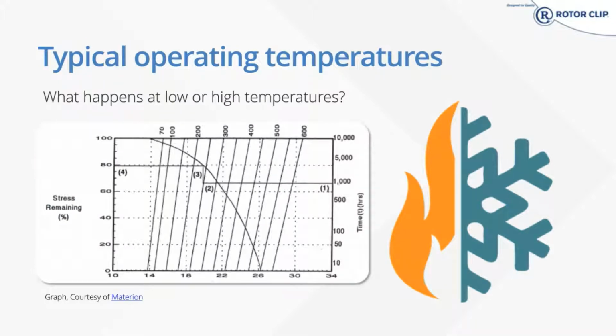So this is a graph that kind of shows what happens at higher temperatures. As the temperature increases, the performance of the ring decreases. So thrust loads are greatly reduced, material strength is reduced, and eventually the parts will fail completely. So if you're pushing the extreme limits of the thrust load of the ring, you usually want to be in the 100-degree Fahrenheit range. You could go 50 degrees below, 50 degrees above. As you start increasing towards the 400 degrees, 300 degrees area, you start to lose performance, and then at 600 degrees, complete failure usually.